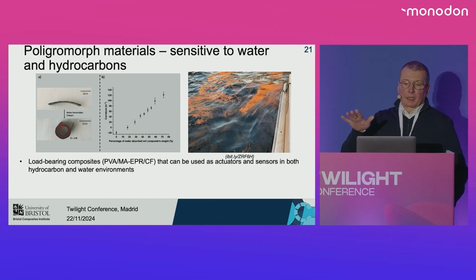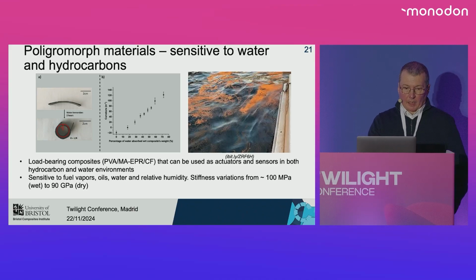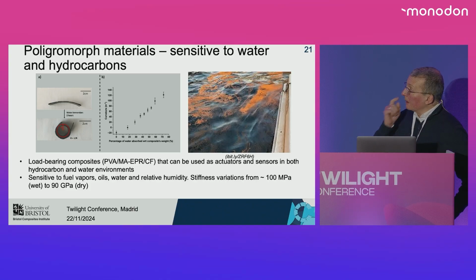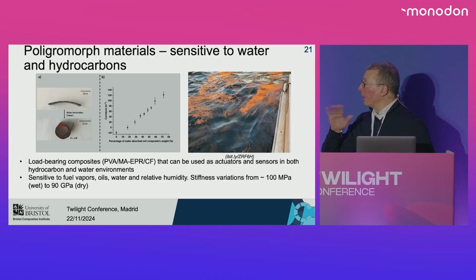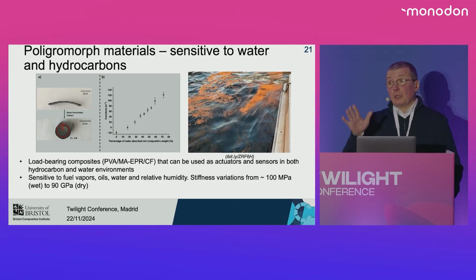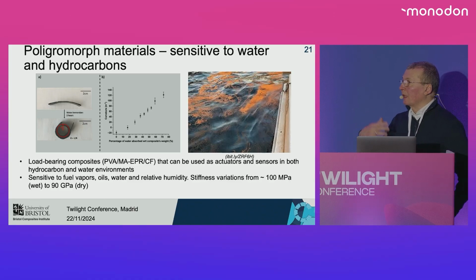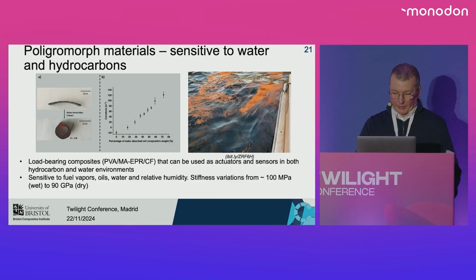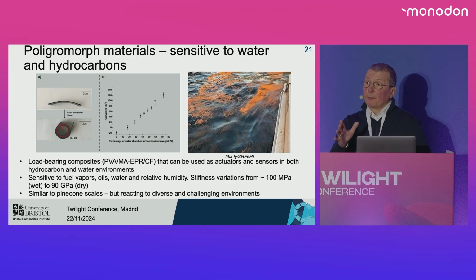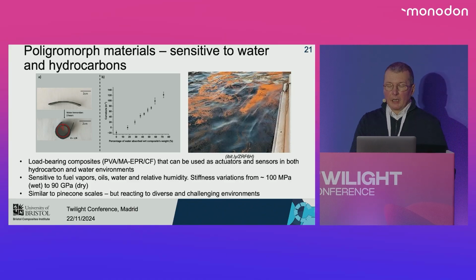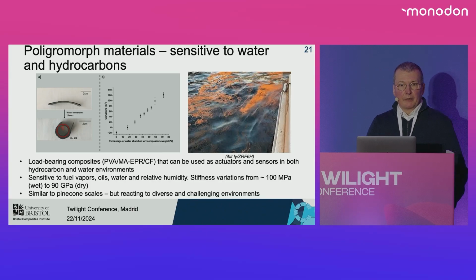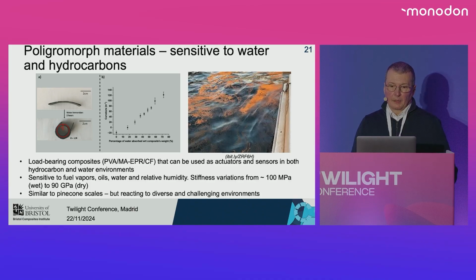And those composites can be used as actuators and sensors, in both hydrocarbon and water environments. So they are sensitive to fuel vapors, oils, water and relative humidity, and quite interesting, the stiffness varies from the wet state from around 100 megapascal up to 90 gigapascal in tension. So we are talking about some considerable load-bearing characteristics. The architecture is very similar to the pinecone scales that we have seen before, but again, they react to different surrounding environments. I would say also more challenging because oil spillage is still an ongoing problem.